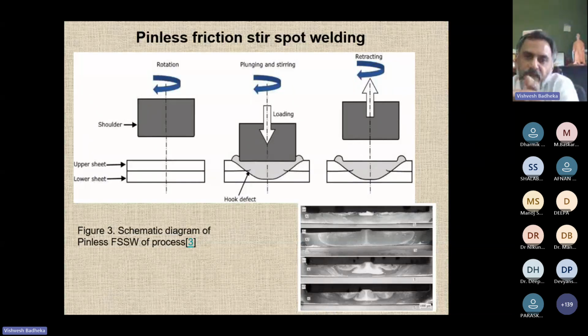Moving further, here also the purpose is the same. Why have they developed pinless friction stir spot welding? Because they don't want that hole which is forming at the end. Why are you getting a hole? Because that hole is because of the pin. So if you remove the pin, is it possible to weld? Yes, it is possible to weld. So they removed the pin and then came out with a process called pinless friction stir spot welding.